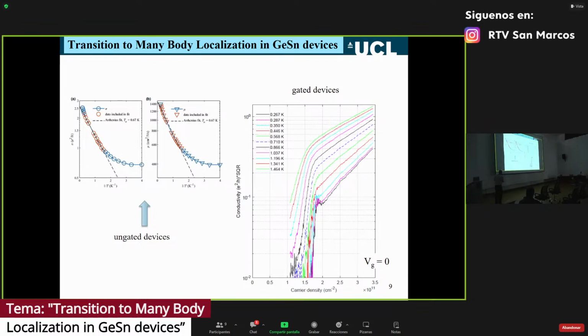What we find is that the mobility is thermally activated with the same characteristic energy as the conductivity. It's this excitation to a mobility edge. If we measure the Hall effect, which we've done to determine the mobility, the Hall effect is constant. There's no change in the carrier density. There's no activation of the carrier density in this system. We move on to the gated devices.